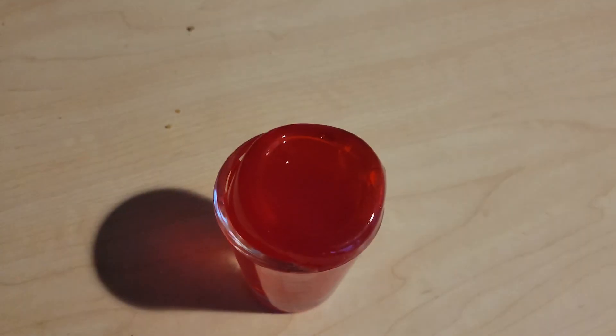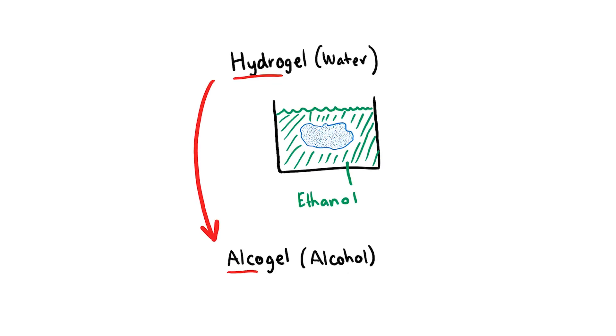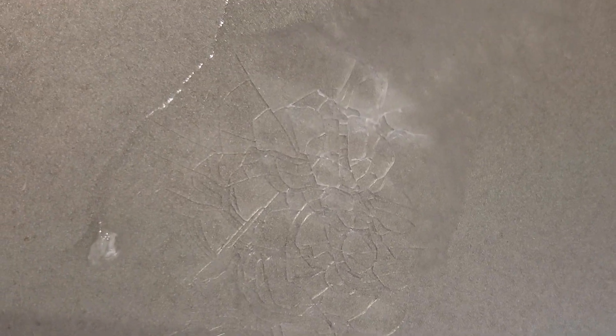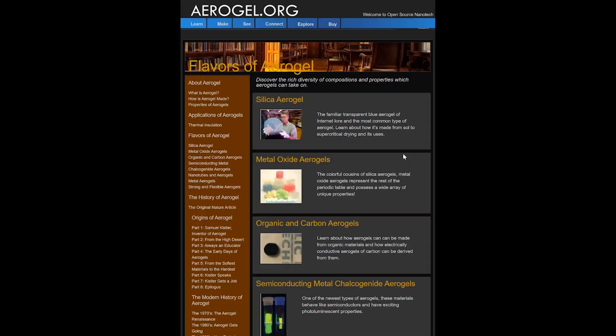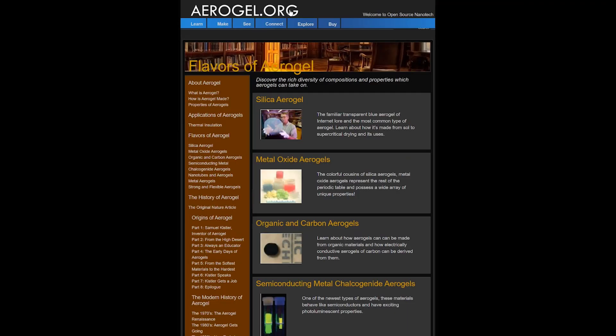Depending on your background, you might know that you can replace the water in jello with other liquids. For aerogel, you do a type of solvent replacement as well, getting the pores to be filled with ethanol instead of water. Then you need to heat and pressurize the gel to above the critical point of the solvent — the pressure and temperature at which you can no longer tell if a substance is a liquid or gas. After reaching the critical point, you need to isothermally depressurize. Supercritically drying the liquid is critical to the operation because it avoids the accumulation of stresses that normally come from an abrupt phase change. Even after all these careful steps, you're looking at a final product that's weaker than the screen of an iPhone 5C. There are many types of aerogels and some are stronger than others, but I chose to oversimplify one technique and one recipe of aerogel just for simplicity. Go to aerogel.org if you want to learn more.